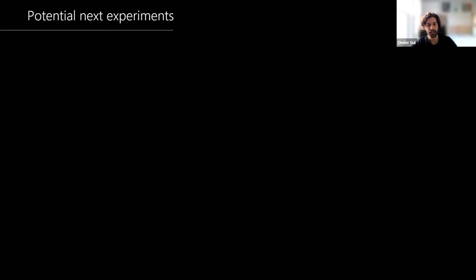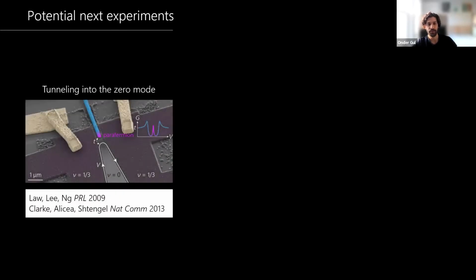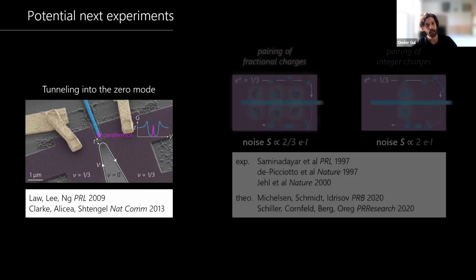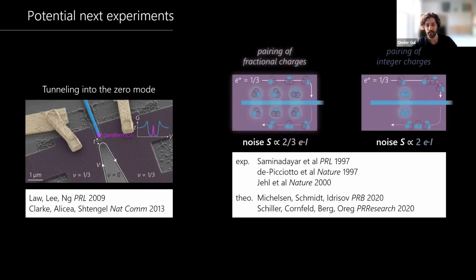Let me quickly flash one slide about potential future experiments. One experiment is to detect tunneling signatures of superconductivity and potentially of a zero mode localized at the tip of the superconductor. Another set of experiments are noise measurements. Noise measurements can reveal the charge of the Andreev reflected holes. If found fractional, this could be an indication for fractional charge pairing. However, if the measured charge is integer, this would mean that the edge state at the superconductor interface is effectively an integer edge, not a fractional edge. A Fermi level mismatch could potentially result in such an observation.